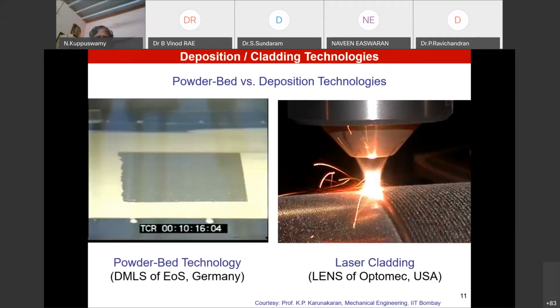Now, let's look at, on the left, the powder bed screen, where you don't see the laser beam movement in this picture. On the right, you have the typical LMD, that is laser metal deposition or direct energy deposition. In the olden days it was called laser cladding, and this is a picture very similar to the LENS model. You have the powder and the laser coming in through the nozzle, and in this case, you are repairing a shaft. I mean, you're not making the whole shaft by 3D printing. You are basically resurfacing the shaft or a roller, which is typically done in the paper industry or other industries. You are rebuilding the portions which have been removed by abrasion in use.